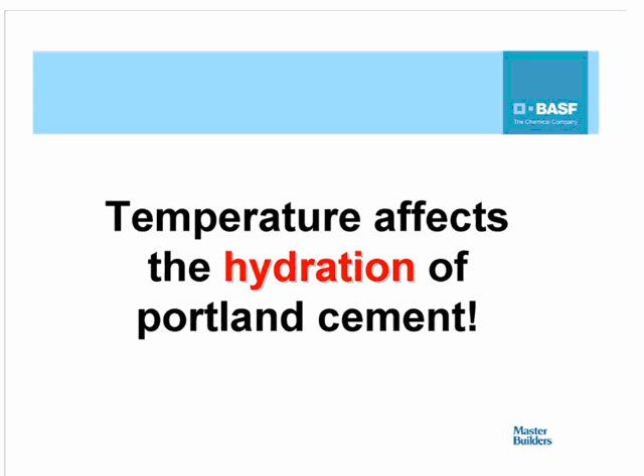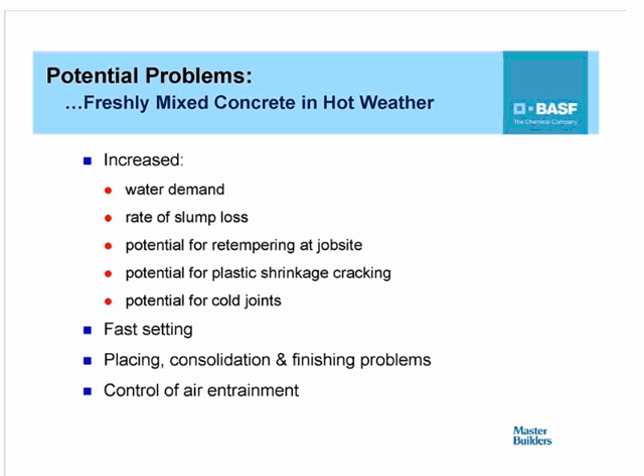Now, temperature affects the hydration of Portland cement, which basically means that in the summertime, the concrete tends to react much faster, and in the wintertime, it tends to react a little slower. As a result, in the summertime, some of the issues that potentially can arise include increased water demand and rate of slump loss for the concrete, an increase in the potential for retempering of the concrete at the job site, a higher potential for plastic shrinkage cracking in the concrete, and if there are delays, the potential for cold joints. In addition, because of the higher temperatures, the concrete tends to set faster, which can lead to problems with placing, consolidating, and finishing the concrete.